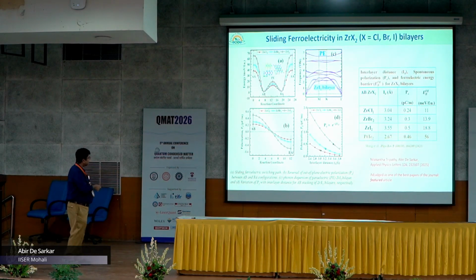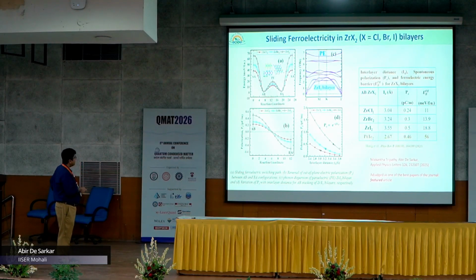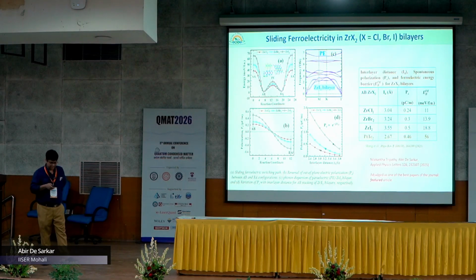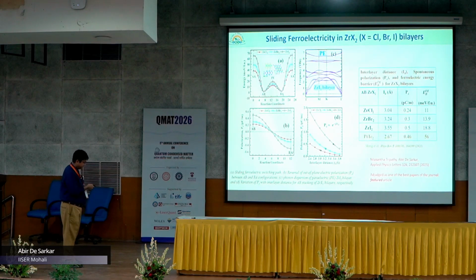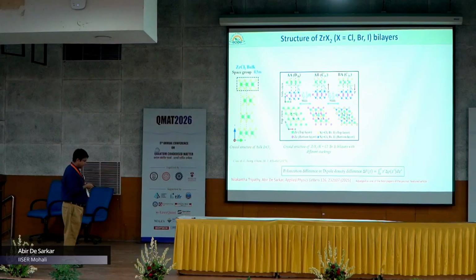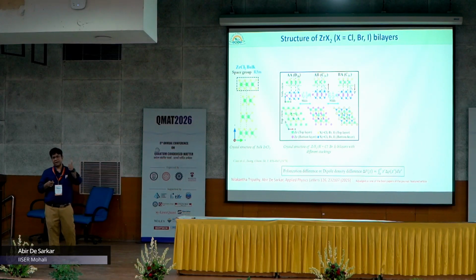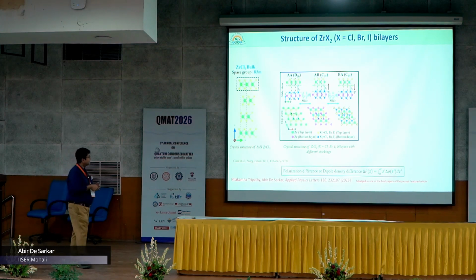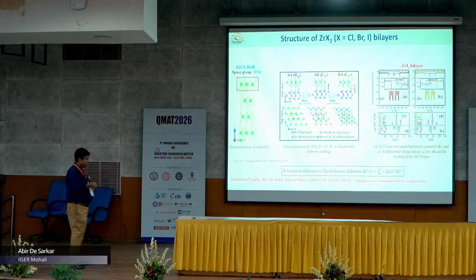And you pass through this centrosymmetric paraelectric phase, which shows instability in the optical phonon modes. That is what we have observed over here. And then we have ascertained the origin of this reversal in the polarization direction as we slide one layer on top of the other. So that arises from the relative electrostatic potential difference between the individual layers.